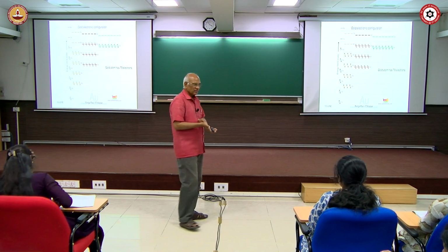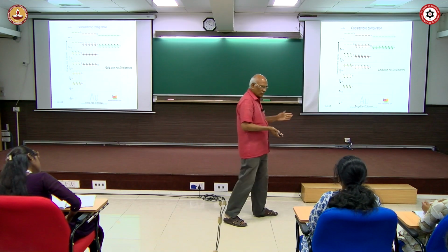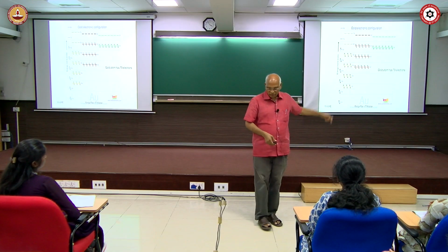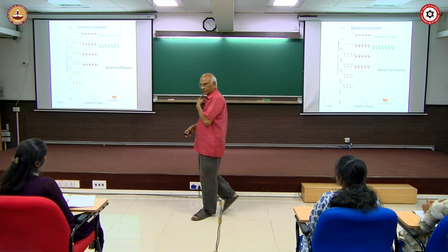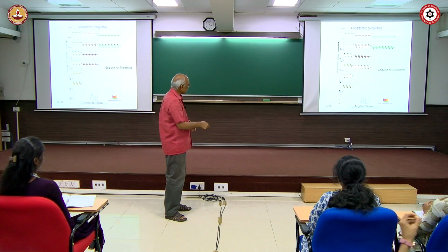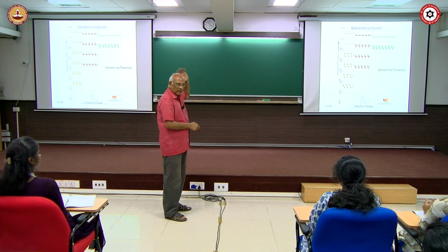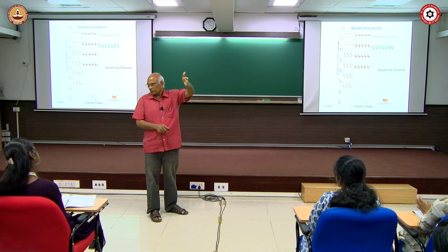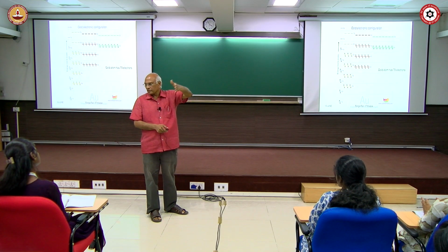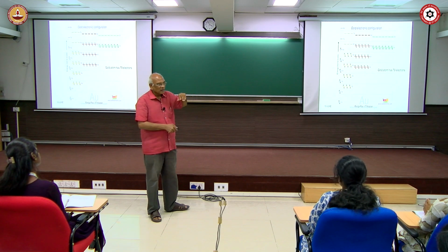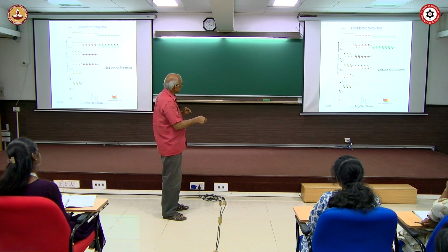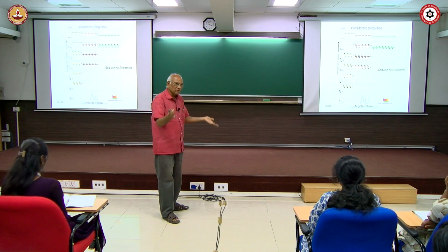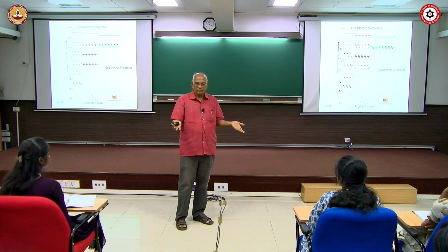Is there any experiment? Photoemission experiment. If we have so many levels, then our photoemission spectrum should show some of them. For example, we may not go all the way to 1s because it requires very high energy. The energies that are available, which we are using, are 1253.6 and 1486.6 electron volts. With that energy, you will be able to analyze only these levels. That is enough for us to analyze the state of the element in the sample.